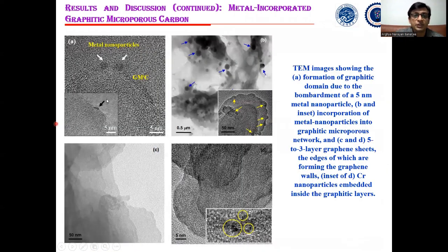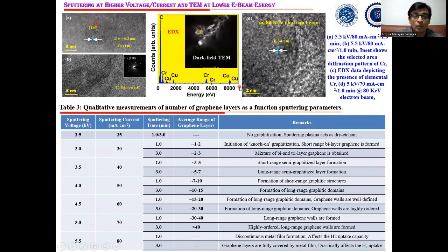So this is actually showing some HRTEM image of the metal incorporation inside the graphitic microporous carbon network. These are some of the metal nanoparticles you can see. Here you can see the HRTEM image of 3 layers of graphene, and this is showing metal incorporation inside the graphene layers. Now, one more thing is that when we increase the sputtering parameter beyond a certain limit, we are observing some metal film formation, or covering of the entire graphitic microporous carbon by metal film.